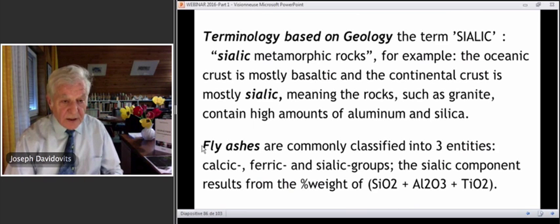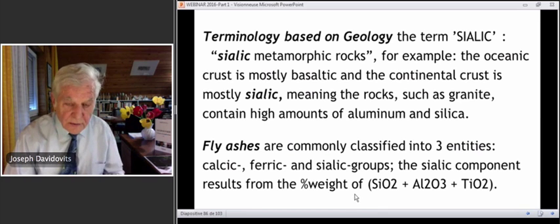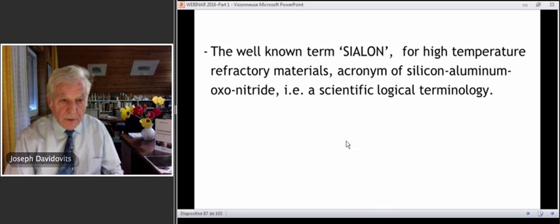We have also fly ashes. Well, fly ashes, we have fly ash class C and class F, but other classifications are commonly classified into three entities: calcic, ferric, and sialic group. The sialic component results from the percent weight of SiO2, Al2O3, and TiO2. These are scientific wordings that are relating to what we are doing. Forget about the saliva of the Greeks and biology. The well-known term Sialon, silicon aluminum oxide nitride, for high temperature refractory material, is the acronym of silicon aluminum oxonitride. It is a scientific logical terminology.